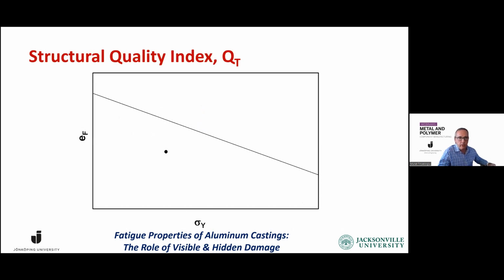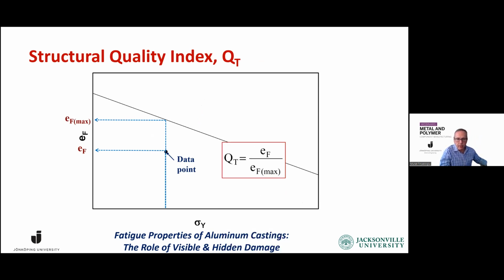Okay, so let's then define the structural quality index. If we have a data point, then obviously we have the elongation. But then we can calculate the maximum elongation that it would correspond to. And then we can define the quality index as the ratio of elongation to the ductility potential, or the maximum elongation we have. So what this also implies is that the remainder is the damage, the loss due to the damage. If we had no damage, we would reach the potential. But because there's damage in the casting, we don't reach that. So this is also a measure of the damage.